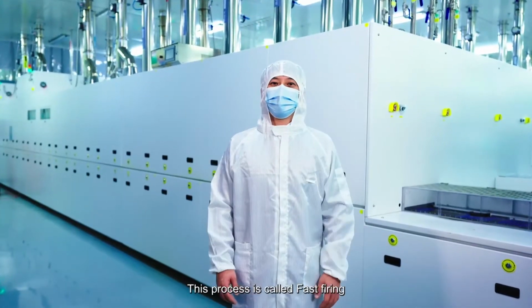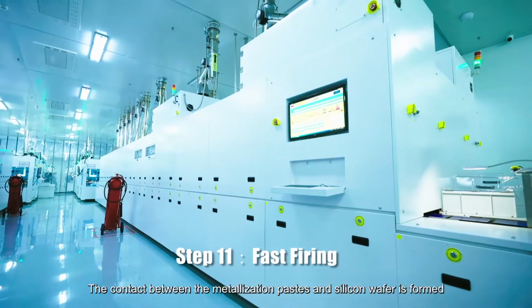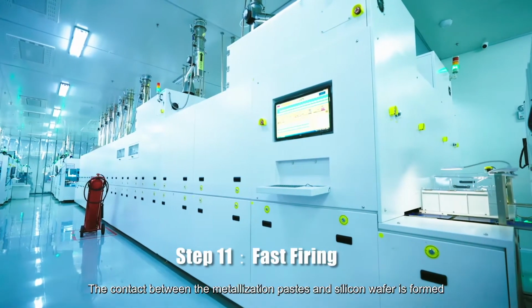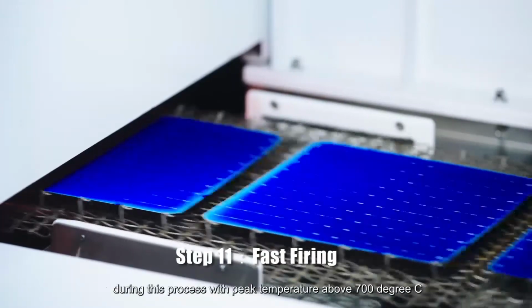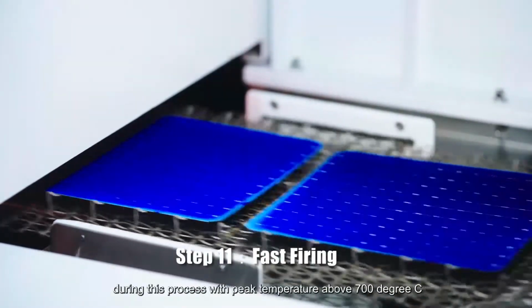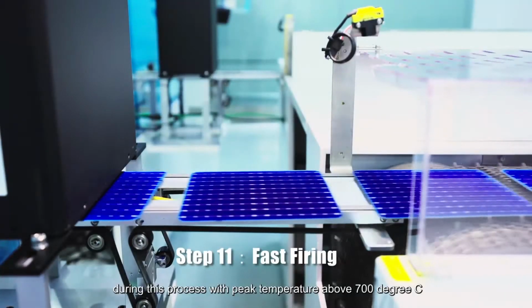This process is called fast firing. The contact between the metallization paste and silicon wafer is formed during this process with a peak temperature above 700 degrees C.